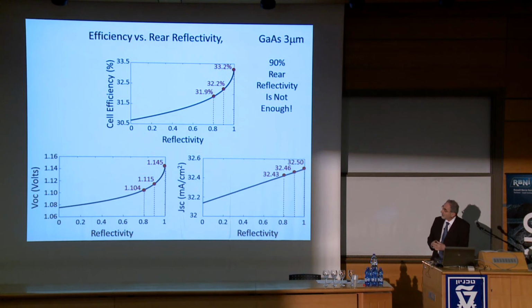If you analyze what the penalty is, you can see by this that the better the rear mirror, this has to do with the rear reflectivity, but it's very similar to the luminescence efficiency, the better you do, but the last little bit gives you the biggest boost. So what it says is that 90% reflectivity is not enough. We would, if possible, like to get up here to 99%. That would be very nice. The entire improvement is due to the voltage becoming much, much better as you improve the optical properties, and the current is almost unchanged. This is all about the voltage.